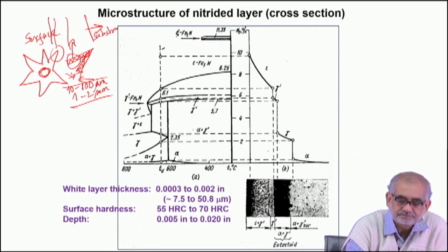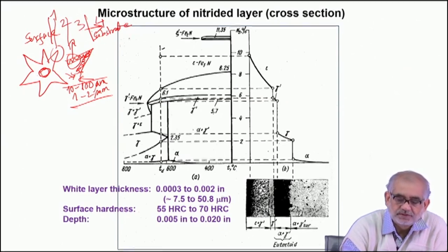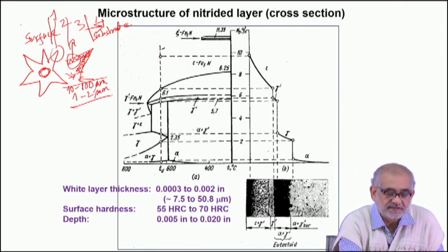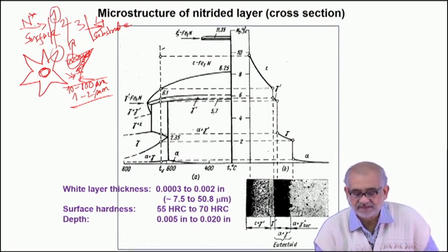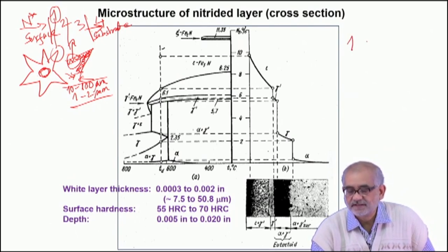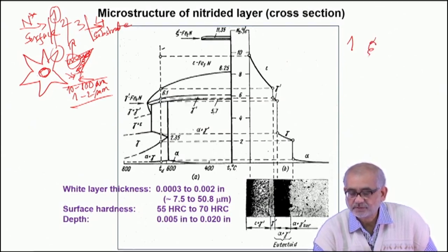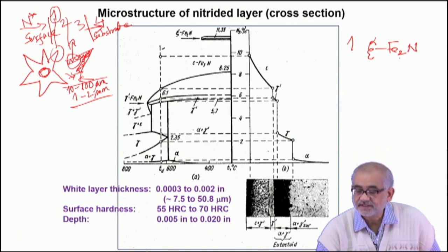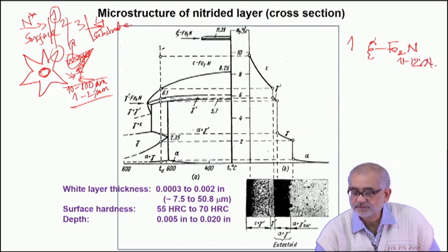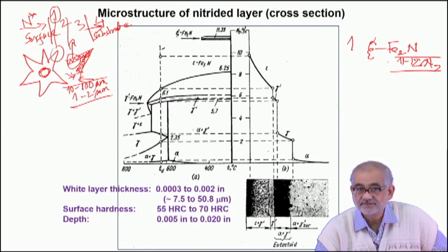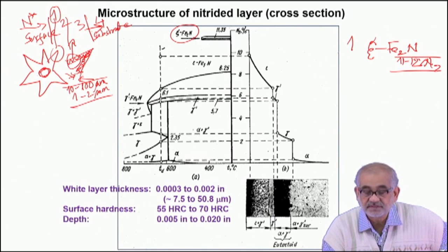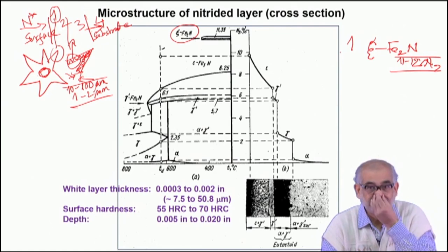In this gradation of regions 1, 2, 3, 4, we have different levels of nitrogen penetration. The surface exposed to the bath has the highest nitrogen concentration. The first layer is where we expect the formation of zeta compounds — zeta is Fe₂N — and this requires as high as 11 to 12 percent nitrogen. This is very high nitrogen; if it forms at all, it is never a single monolithic layer but only dispersed compounds. The zeta Fe₂N is essentially only available as a dispersion or very thin layer at the surface.